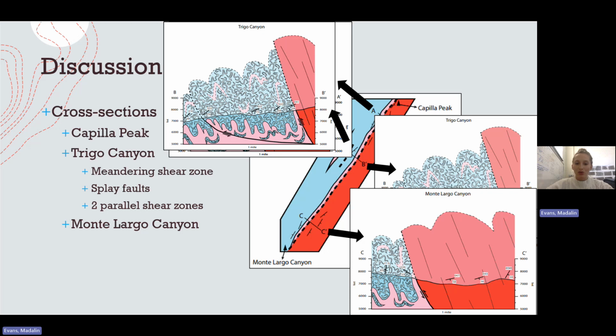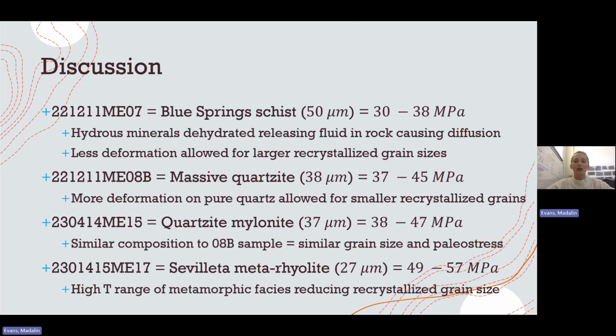And it is quite similar to the very first one I showed you, with the Sevilleta metarhyolite being thrusted northwest up and over the Blue Spring Schist and massive quartzite unit. So all of these lithologies displayed an increasing trend of paleostress as they approached the shear zone. The 07 sample, which was in the Blue Spring Schist, had a mean recrystallized grain diameter of 50 microns with a flow stress between 30 to 38 megapascals.